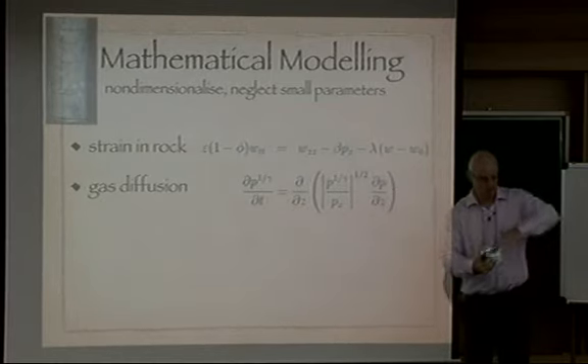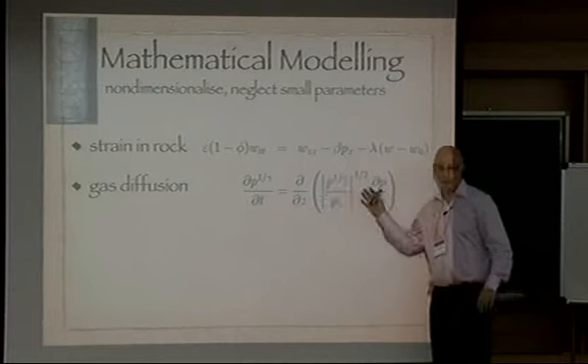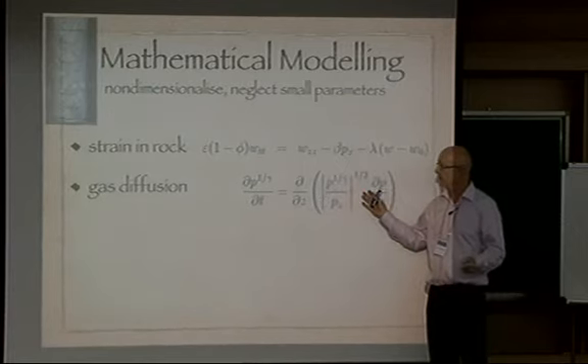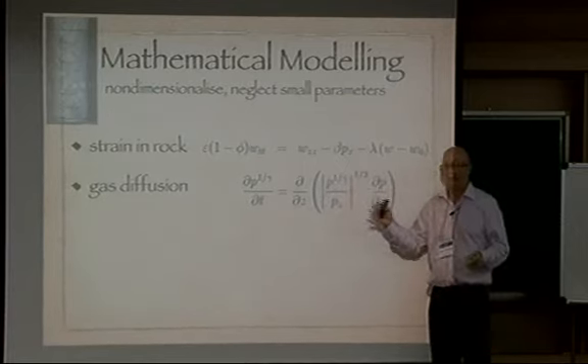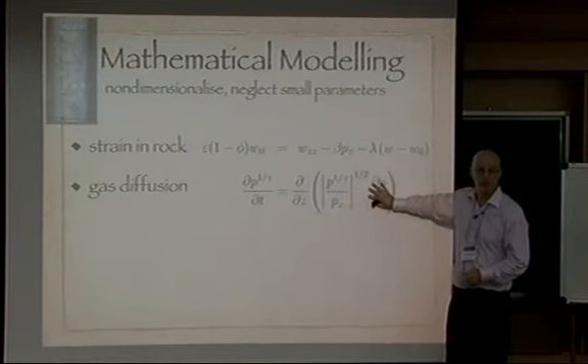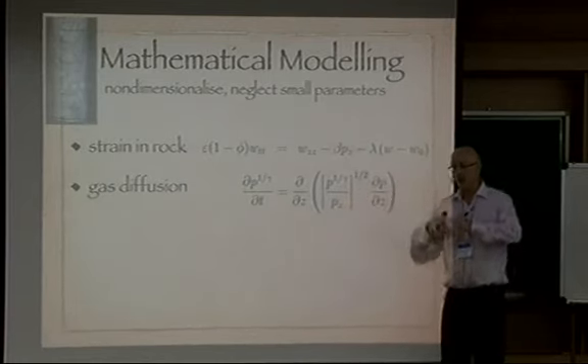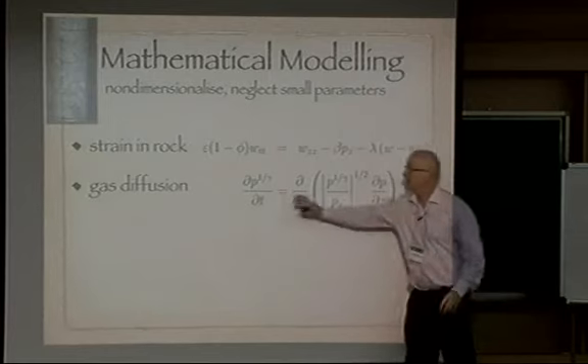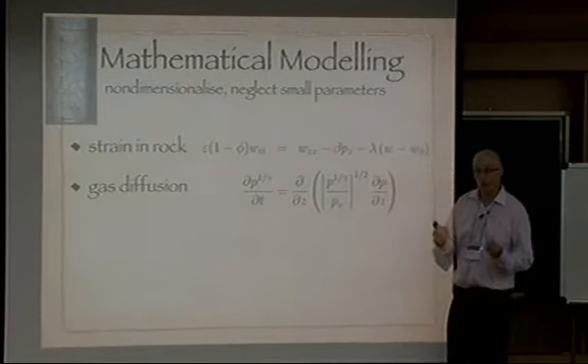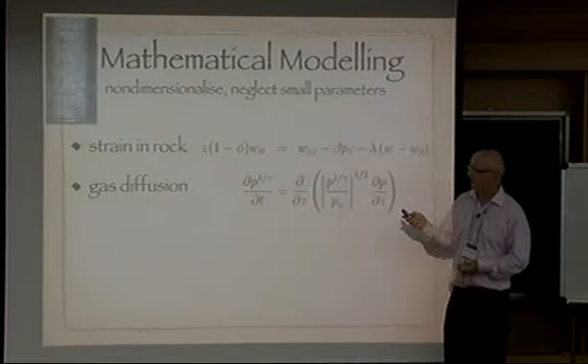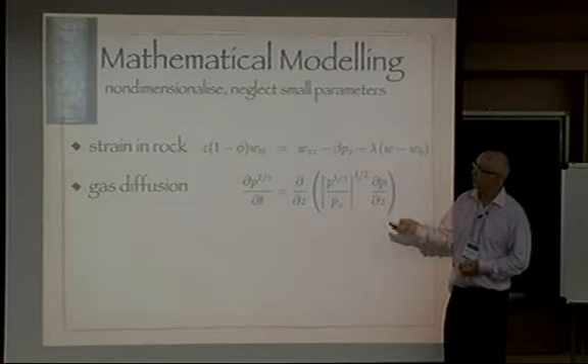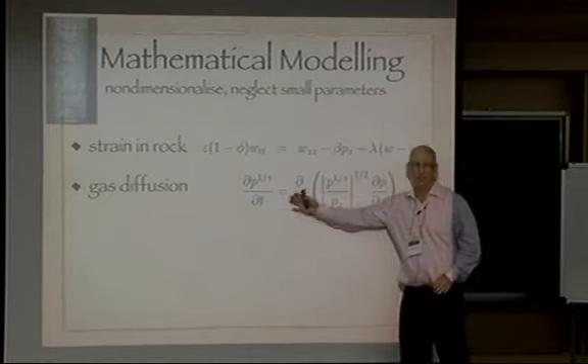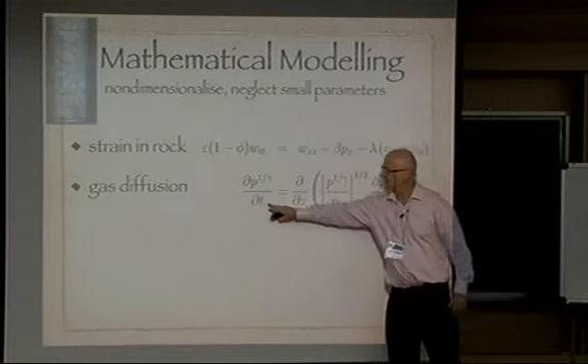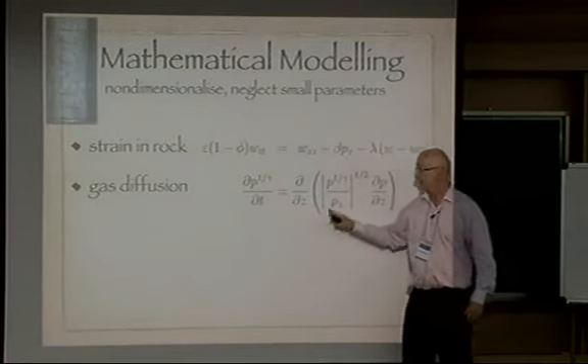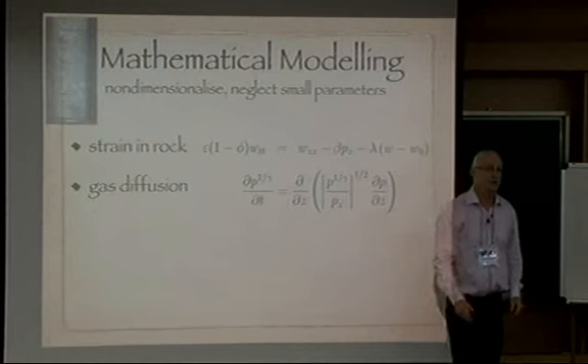We know that it drops, and we can do some analysis of this equation, perhaps in asymptotics. But yes, we know what happens. Just from knowing it's a nonlinear diffusion equation, we know that the pressure drops and goes through, and it drops on the time scale that we're talking about. So we've got the right time scale. The non-dimensionalization that gave us this equation is almost more important than the equation itself. There are no parameters in here anymore. All the parameters are buried in the non-dimensionalization, so they give us t, and we need z values.